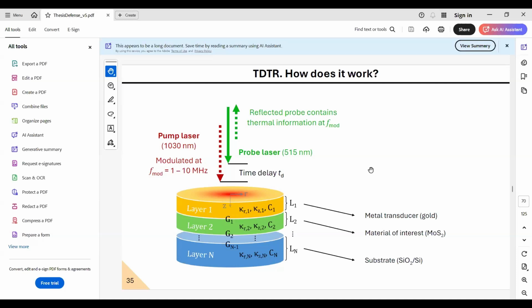Then I have a question about the interfaces and geometries, right? Because as you're transferring the flakes with PDMS, and I love PDMS transfer, but I'm also aware of the limitations of PDMS transfer, and it's not the cleanest transfer, so you can leave residues. How can the residues of PDMS affect, for example, if you have residues on the clamping, on the freely suspended layers, or if you have residues in between the flake and the silicon oxide in the TDTR measurements? How can that affect the measurement? I think this is a very important question.